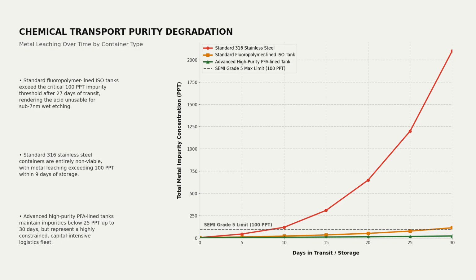This deficit cannot be resolved through standard transoceanic shipping. Semi-grade 5 acid is highly reactive and leaches metals from container walls over time. Standard fluoropolymer-lined tanks exceed the critical 100 parts per trillion impurity threshold after 27 days in transit. Only specialized, capital-intensive PFA-lined containers can preserve purity, but their global fleet is highly constrained.